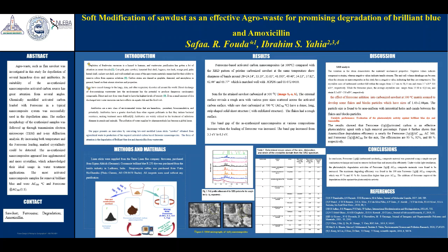Ferrocene based on activated carbon nanocomposite at 500, compared with XRD of pristine carbonized sawdust at the same temperature, shows 2 theta at 24, 33, 35, 41, 49, 54, 57, 62, and 63.77, which matched well with card number 01-072-0450.